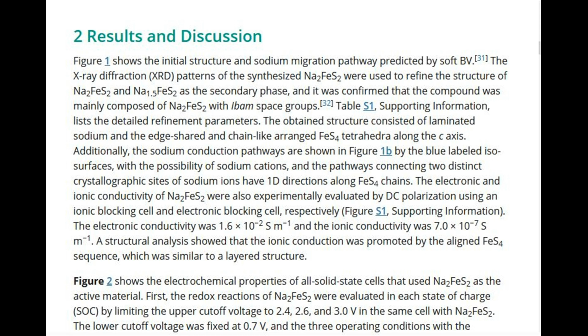Figure 1 shows the initial structure and sodium migration pathway predicted by softBV.31 The X-ray diffraction (XRD) patterns of the synthesized Na2FeS2 were used to refine the structure of Na2FeS2 and Na1.5FeS2 as the secondary phase, and it was confirmed that the compound was mainly composed of Na2FeS2 with Ibam space group.32 Table S1, Supporting Information, lists the detailed refinement parameters. The obtained structure consisted of laminated sodium and the edge-shared and chain-like arranged FeS4 tetrahedra along the c-axis. Additionally, the sodium conduction pathways are shown in Figure 1b by the blue-labeled isosurfaces, with the possibility of sodium cations, and the pathways connecting two distinct crystallographic sites of sodium ions have 1D directions along FeS4 chains.